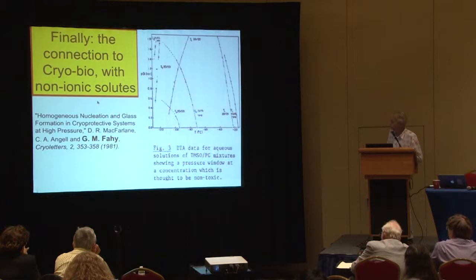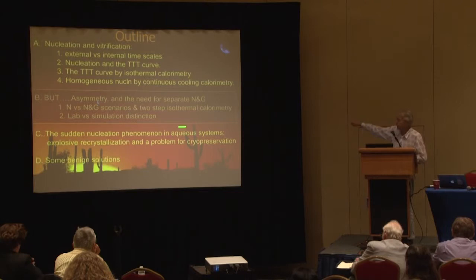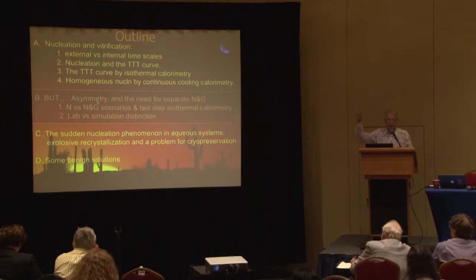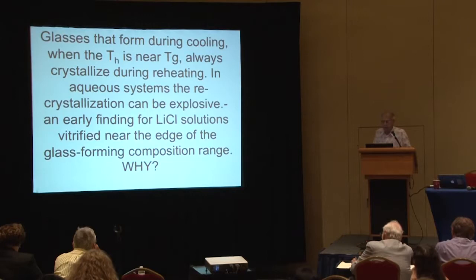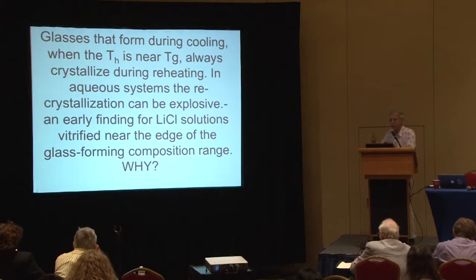Okay, so now I come to the second part, which is important to deal with, this asymmetry in the vitrification and subsequent warming, because so far all the figures I've shown you are determined by waiting for roughly 50% of the available water to crystallize. That requires a lot of growth of the nuclei, so it's not just nucleation.